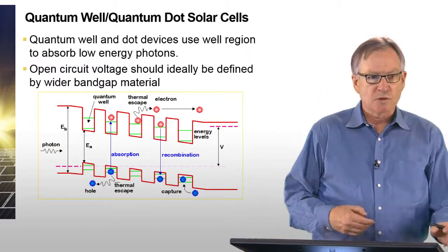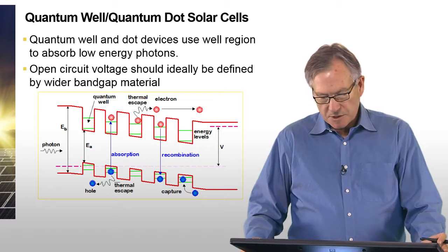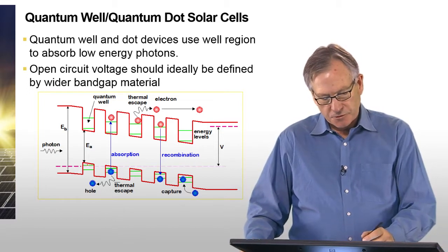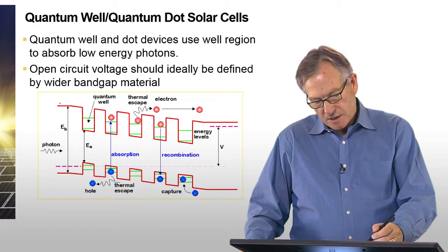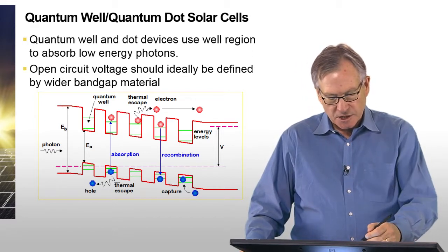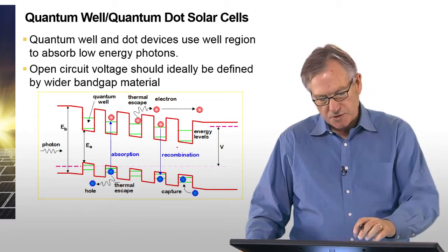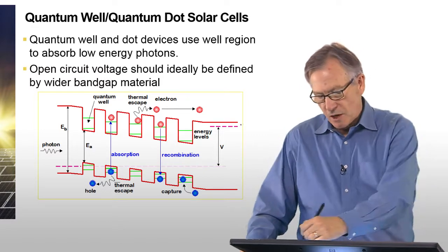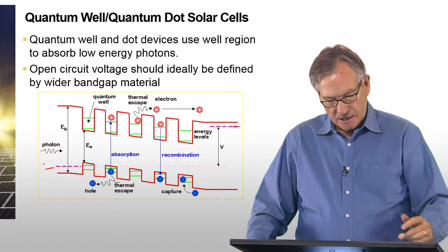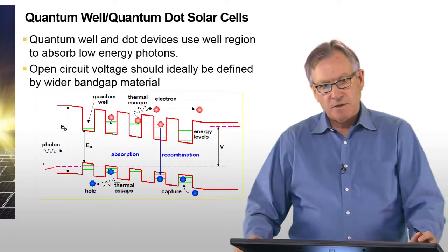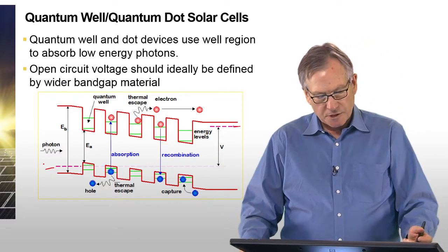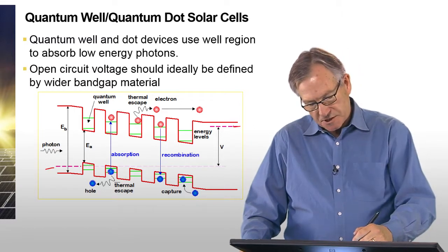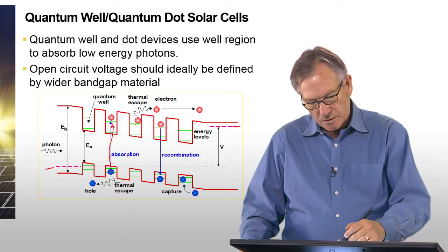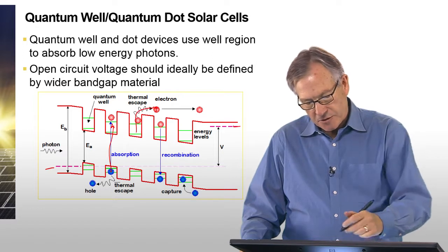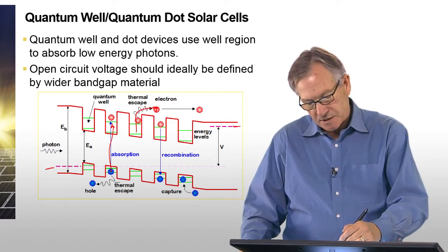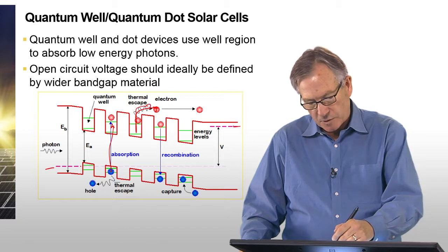Another approach is using quantum wells. As I mentioned, quantum wells also introduce intermediate levels, and so you can think of this as being, say, gallium arsenide, and these are indium gallium arsenide quantum wells, which have a smaller band gap. Contact is made to the gallium arsenide, P and N, and that ultimately can control the voltage. But you excite electron hole pairs within the well, and either they can escape by thermal activation or they can escape by being promoted by another photon out of the well.